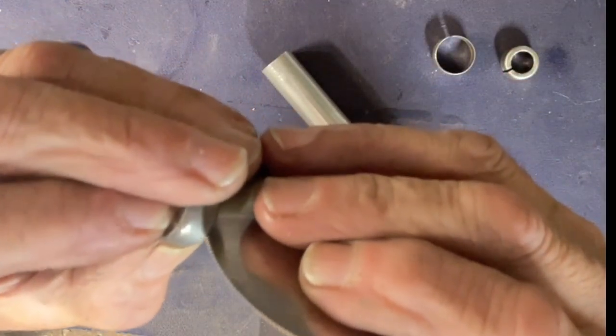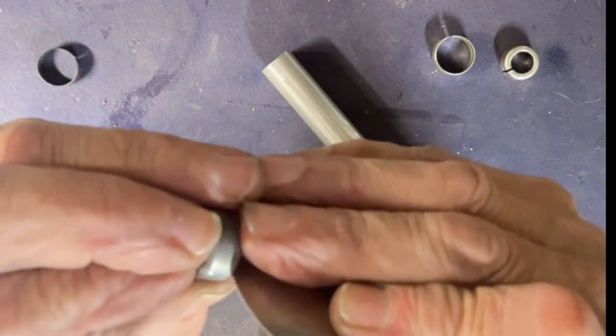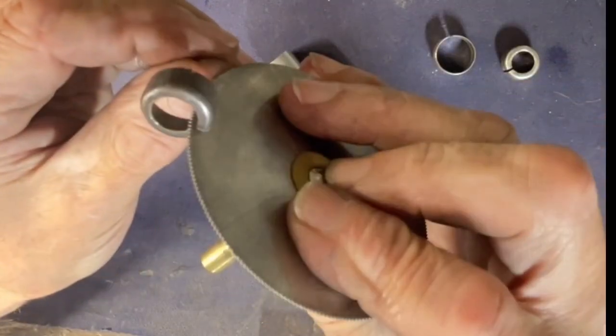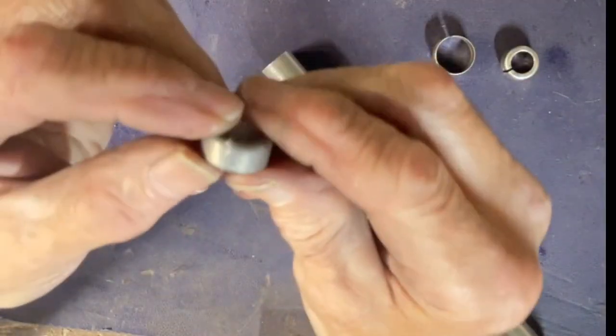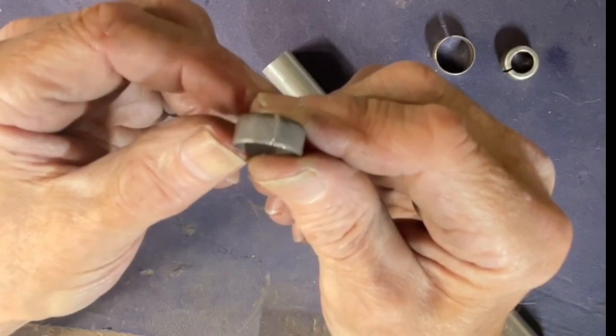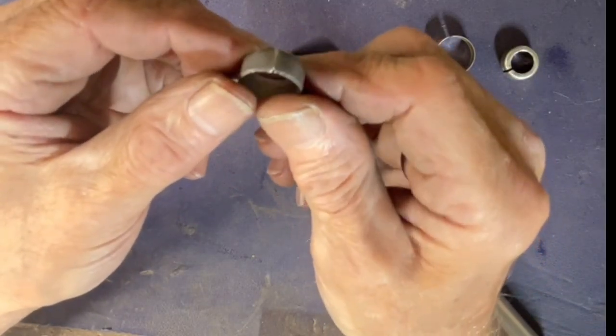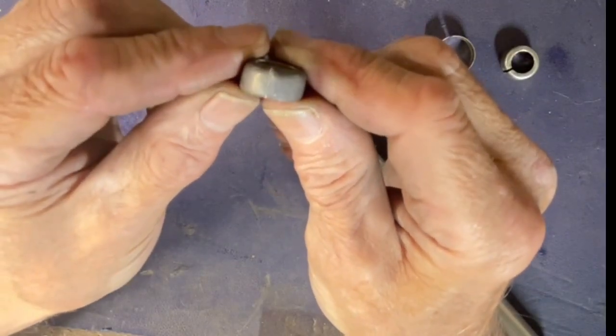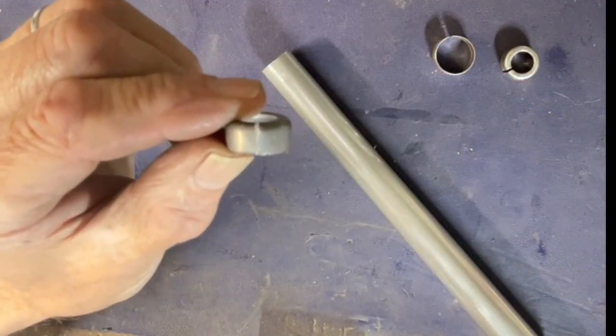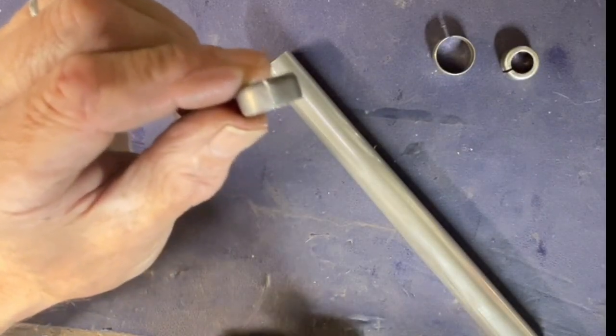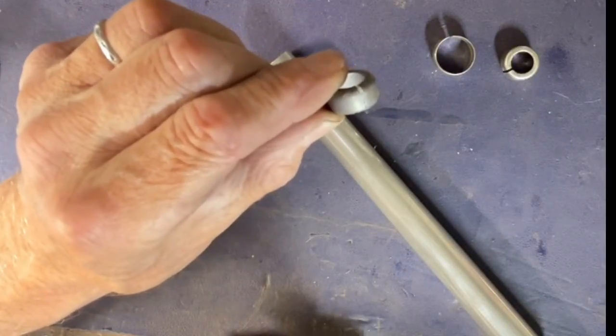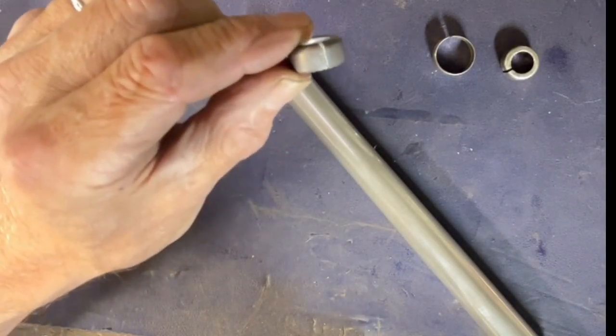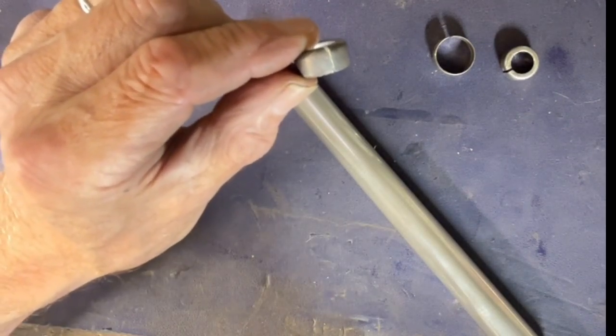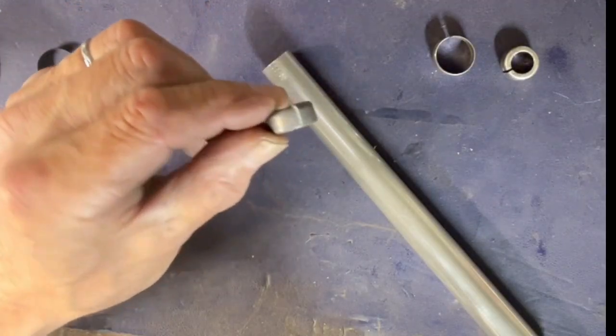So this kind of stress relieving is something that's generally done in a kiln. It can be done in a household oven for silver, something around 530 degrees Fahrenheit, which is pretty hot for a household oven, for an hour. I know people who use a torch and try to get this straw colored, but in general, if I'm going to heat treat something, I'll use a kiln so I have an exact temperature, and I change my time settings all the time as I'm keeping accurate records and finding how the results fared.